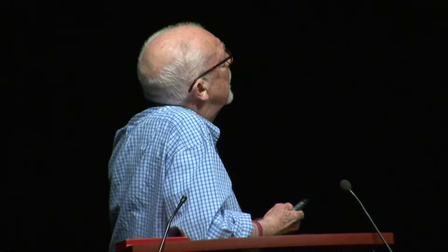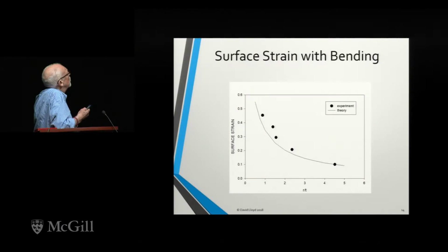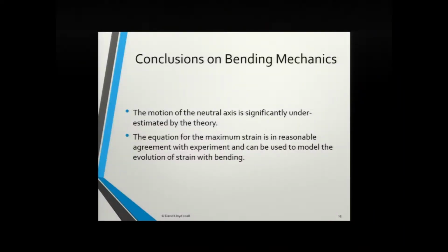You can see that in this particular case, we're looking at a global microscopic surface strain of about 0.45, that sort of order in this particular case. So what do we get? What conclusions can we make from the bending mechanics then?